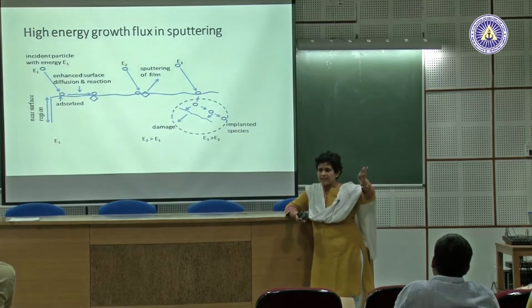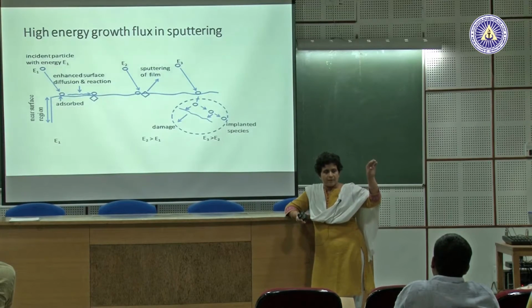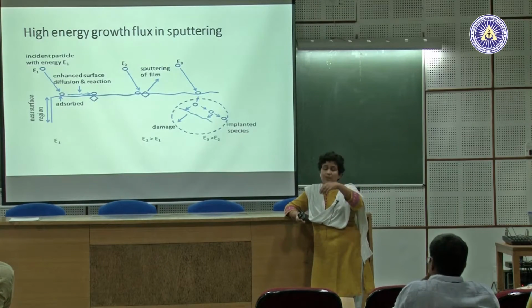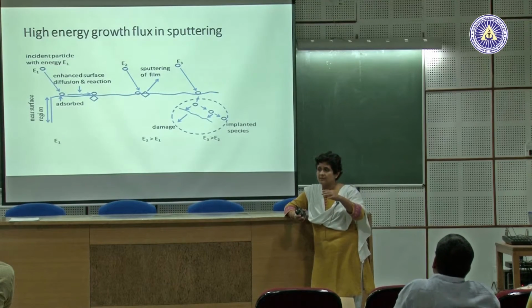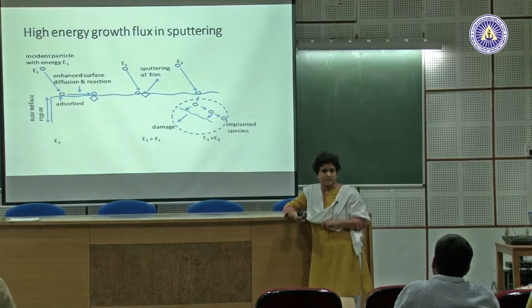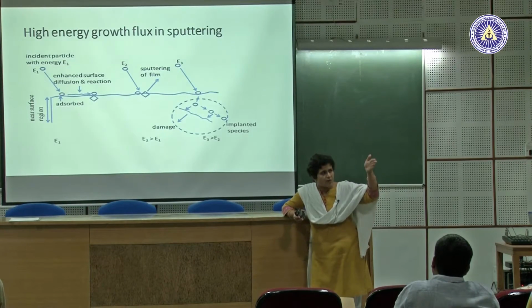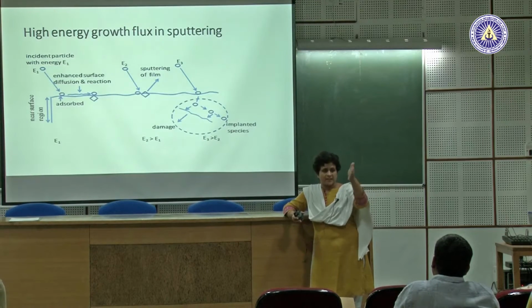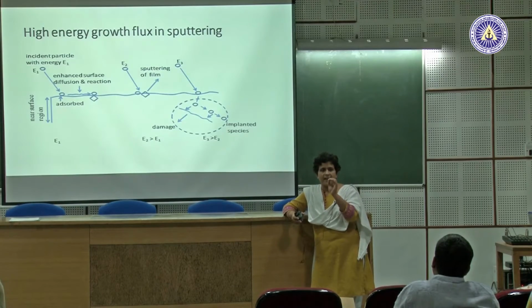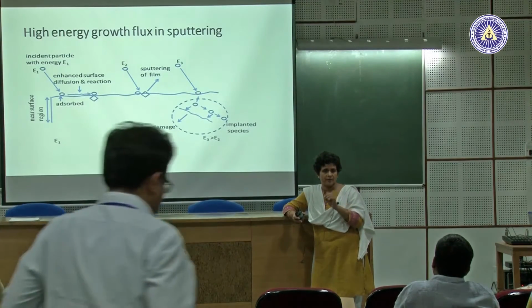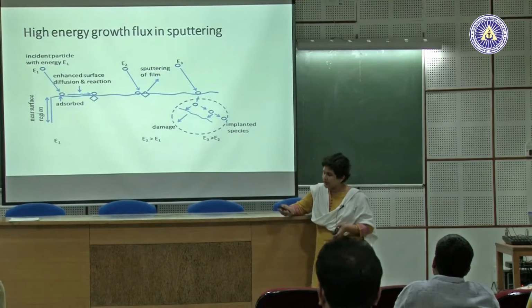So basically there is a whole energy range. If the energy is low enough, then it would just get deposited. If you keep increasing it, it will start sputtering. If you keep increasing it further, what will happen? These ions are coming, and if you keep increasing the energy, although that is not possible in plasma, but if you could keep increasing it, that atom will go inside the material and get implanted. That is called implantation, right? So there is a whole range of how you control the energy of the species that is coming, depending on what technique you use, plasma or a discharge gun or some other process. You can control where that atom goes and how it is interacting with the surface. Okay, so a huge range of techniques come out depending on that control.